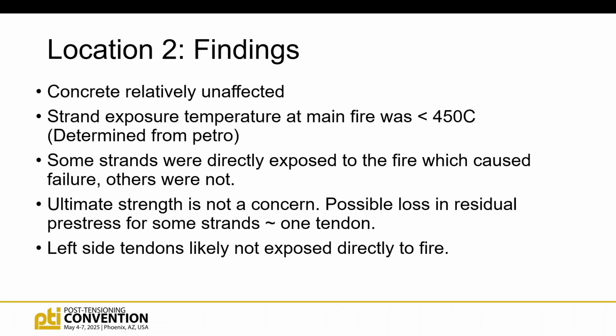Some of the strands, as I mentioned, were directly exposed to fire, which caused their failure, and then others snapped because the load then transferred to the remaining strands, and they couldn't carry that force. The ultimate strength in the tendons, so fpu, we determined through testing was not going to be a concern. There was a possible loss in residual pre-stress, so that's fps in the codes, and we estimated that between 10 and 12%, and once again, that's what Volkert was able to use to reanalyze the span,